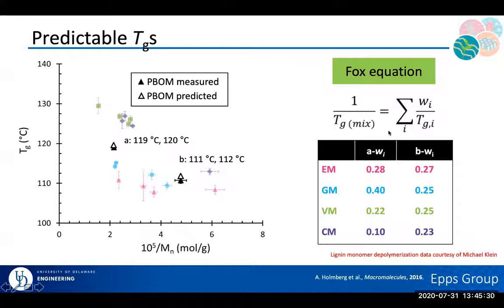What we could then do, because we have homopolymer data shown here for each of the polymers and the expected compositions, is calculate the glass transition temperature of a polymer if we were to mix these feedstocks together. And so those two examples, A and B, are shown here with the predictions in the open triangles. Now what we could do is actually do that depolymerization process, clean up our resulting product, functionalize it, polymerize it, and then analyze it via differential scanning calorimetry, or DSC. When we did that, we actually got the solid triangle shown here.